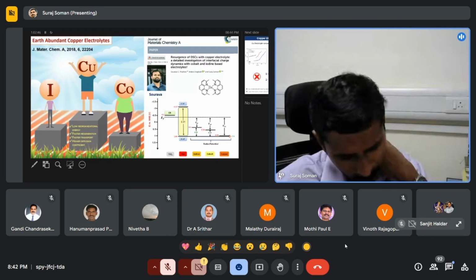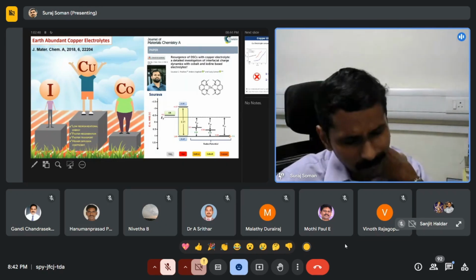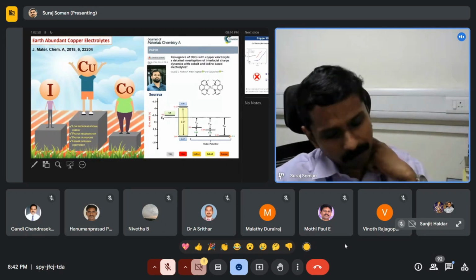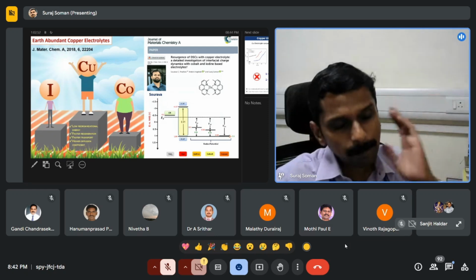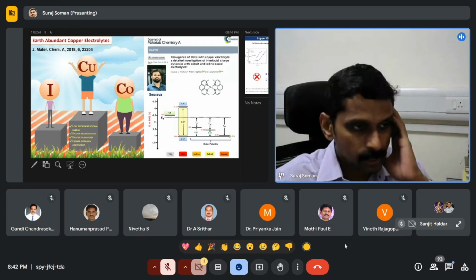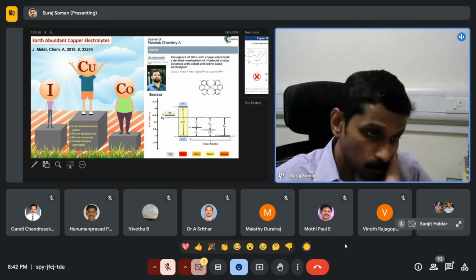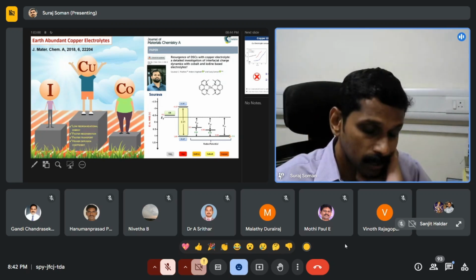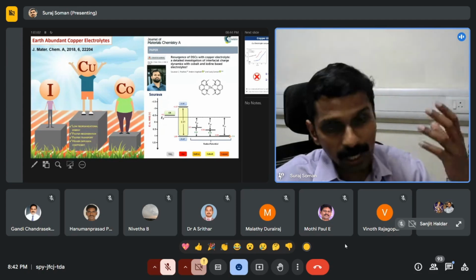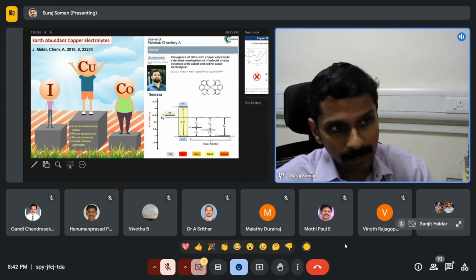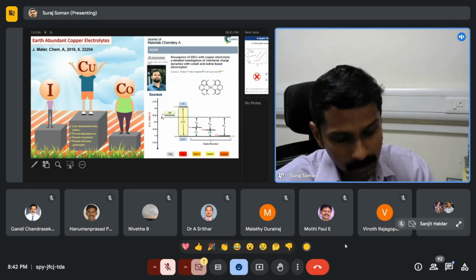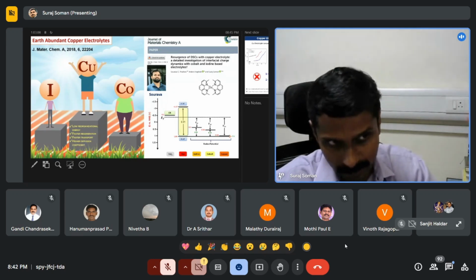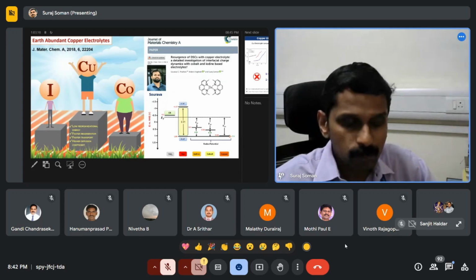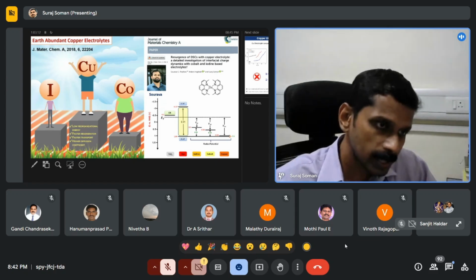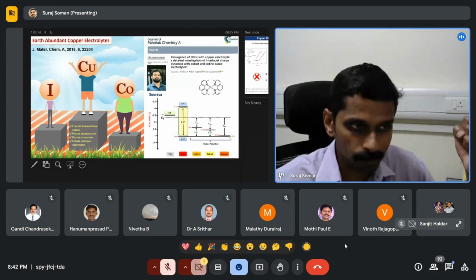Because iodine is fine, good, easily available, but it is corrosive. And from a scale up perspective, it has a lot of limitations. So there we wanted to have an alternative. So cobalt is another component which is being used, but cobalt is a bulky molecule because it's a hexadentate system. You have 3 polypyridyl ligands attached to your cobalt metal center. So it becomes more bulky. So the movement of the ions inside the electrolyte becomes a problem.